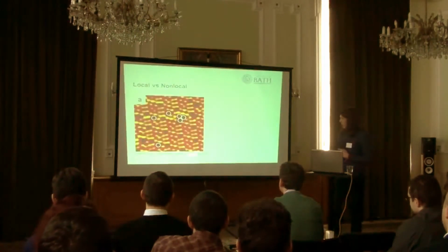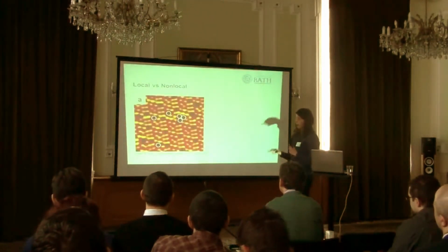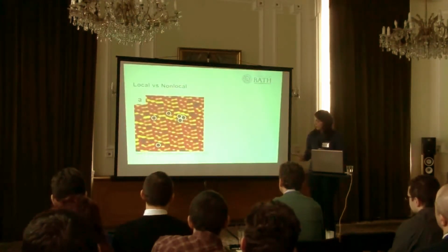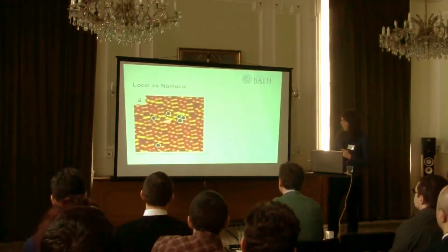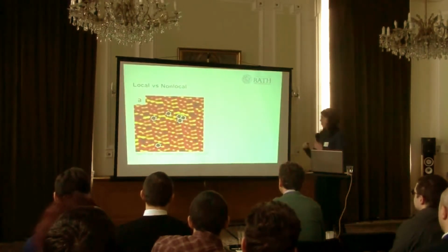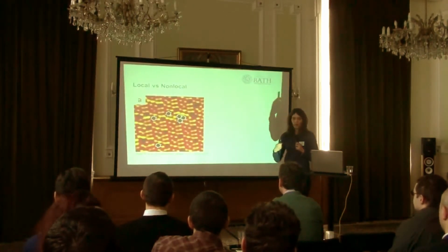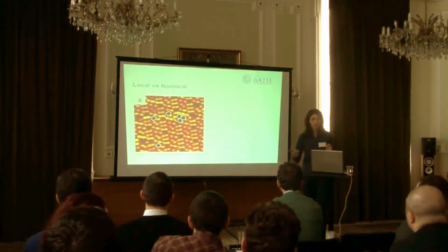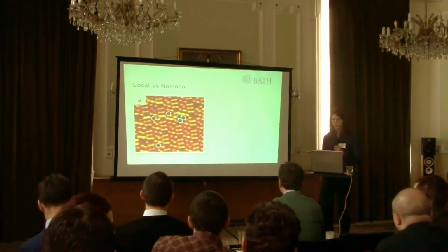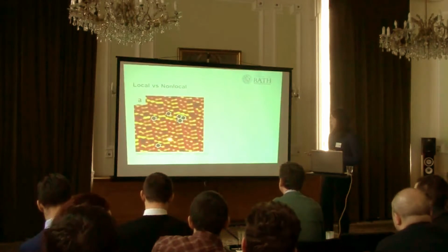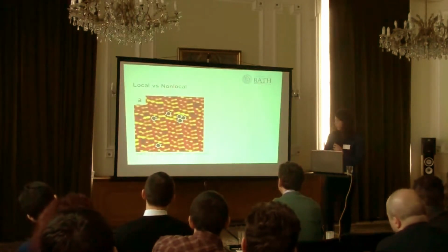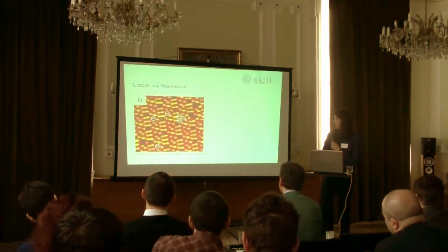So what we do is we take the silicon surface and we put some molecules on it. And these dark spots on our silicon surface are actually molecules. If we increase the scanning bias, the bias at which we're scanning, so we're now using high energy electrons, or high-ish, we're still in a few eV range, so they're not actually really high. So if we increase the tunneling bias and scan over again, these molecules are going to leave the surface,